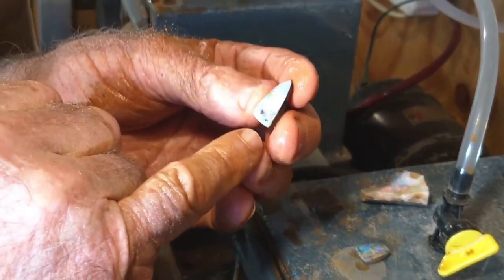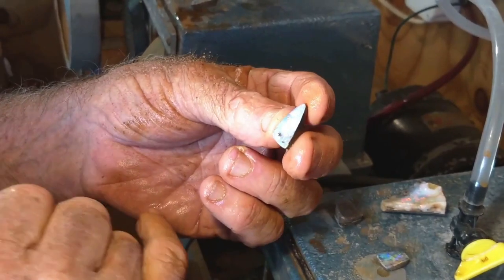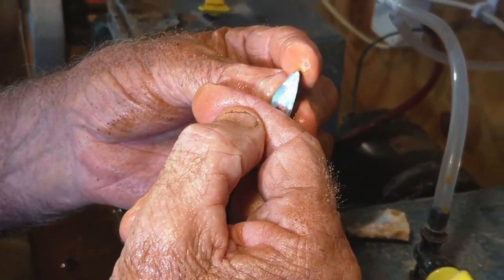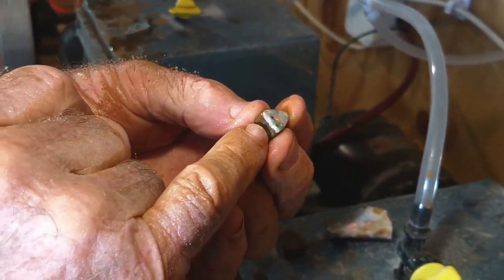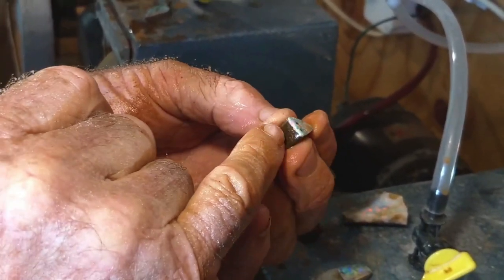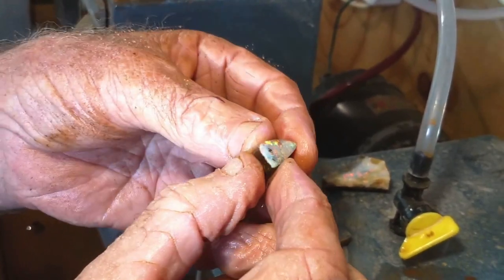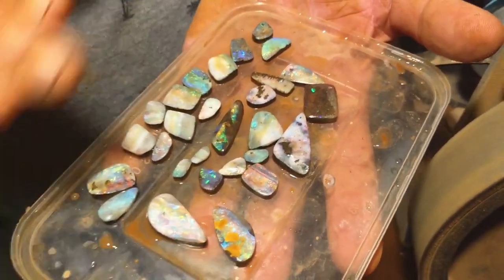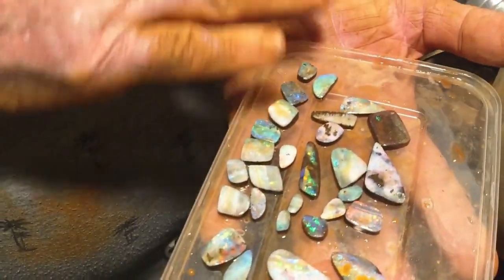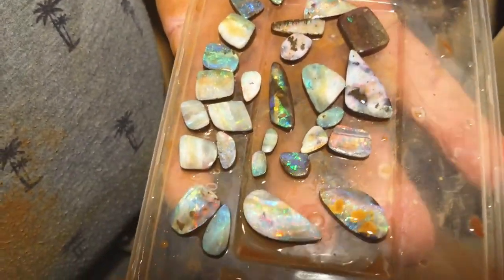The decision now: there are two little spots of ironstone in the face. The choice is to leave them there or grind them away and lose that much stone. There's nice color down in the lower part. As the seam gets a little thinner on the sanding discs, some of that ironstone may disappear — it's always a little bit of cutting and a lot of looking and thinking. Sometimes there's stress in the opal when the boulder miners split the boulders, so Rod shapes it to approximately its final shape and leaves it for two or three days. He'll dress the backs, put them on dopsticks, and then work them on sanding discs to their final shape and then to polish.